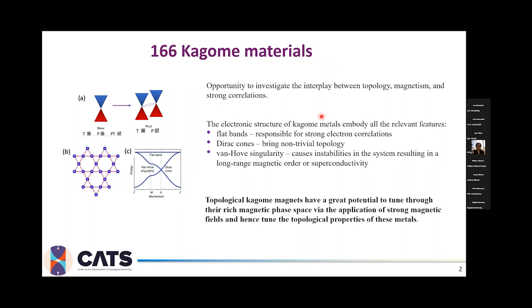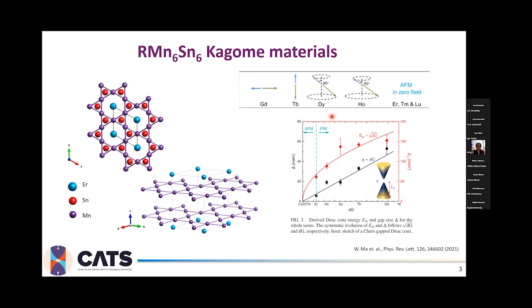The interesting point is that many of these materials show very strong, complex magnetism, and as we know, long-range magnetic order might break time reversal symmetry, and as a result we might also be able to observe the Weyl state in this family. It also shows the Van Hove singularity, which causes instabilities in the system, which may result in long-range magnetic order and also in superconductivity. So I would like to point out that these materials have great potential to study, first of all, the complex magnetic phase diagram, and also to investigate how different magnetic spin textures influence the possible topological properties. So here is the structure of this material.